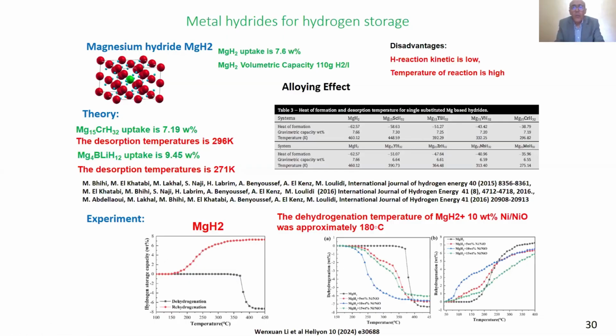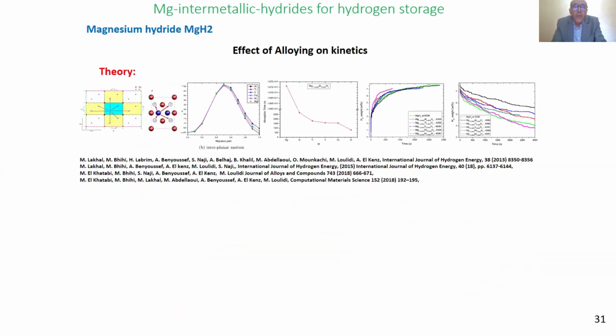This result has also been obtained experimentally with some substitution. It is possible to reduce the desorption temperature and also to improve the kinetics. This study has been done using kinetic Monte Carlo simulation, by first calculating the best position for the adsorption of hydrogen, and then calculating the activation energy, which means the diffusion barrier.